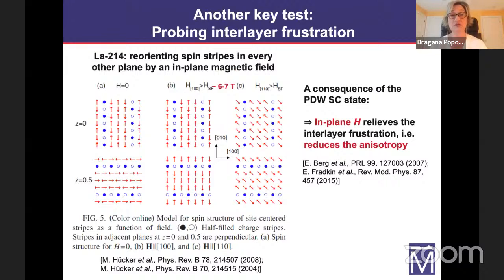So in these lanthanum 214 cuprates with stripes, it turns out that an in-plane magnetic field is actually a suitable perturbation, because it is known that a sufficiently high field can lead to a spin-flop transition in every other plane. In other words, a sufficiently high parallel magnetic field will reorient the spin stripes in every other plane, and within the paired density wave picture, this should reduce the frustration of the interlayer Josephson coupling, and therefore the anisotropy should be reduced. So this is exactly what we tested and what we observed, as you will see.